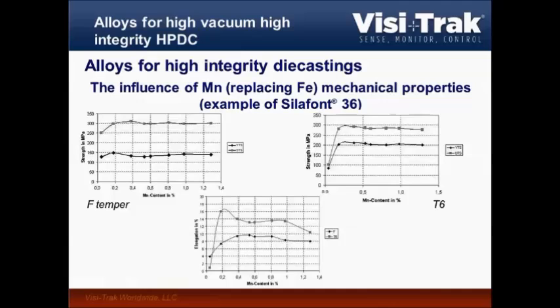Now it was found back in the 90s in Europe that manganese is ideal for replacing this iron. So the first structural alloy available back in the 90s was the so-called Silafont 36, still around, still used very often. And back then it was found that if you go up to 0.8 or even 1% of manganese addition, it doesn't really do much harm to your properties. It actually just improves your properties.